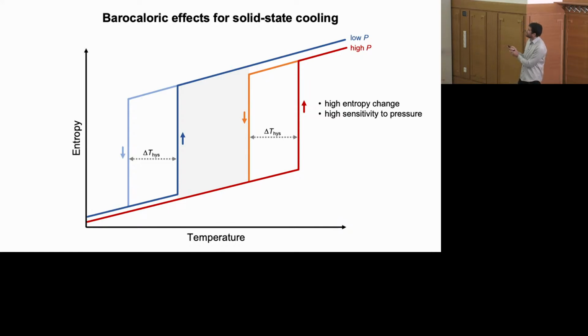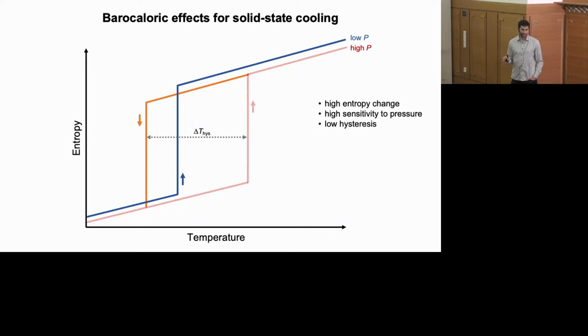And the magnitude of thermal hysteresis, the difference in temperature between the forward and reverse transitions at a given pressure, has a direct impact on the efficiency of a given cooling cycle. It also impacts the pressure that's required to drive a phase transition in a material reversibly. So if you have large hysteresis in your material, you have to go to much higher pressures in order to induce the phase transition in a reversible rather than irreversible fashion. And we'll return to this point a little bit later.